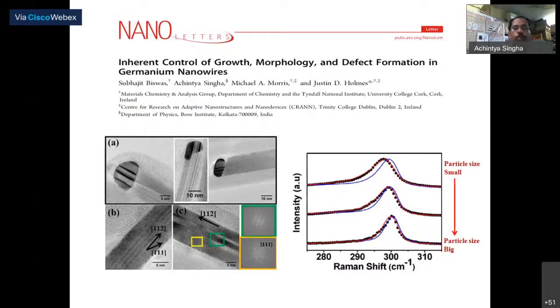Yeah, here is the example of germanium nanowires of different size. You can see the Raman spectrum on the right side of the slide. You can see that the particle size is decreasing. The upper one is the small particle size, and the lower one is the biggest particle size. When the particle size is big, it is more symmetric, and as we decrease the particle size, this asymmetry appears. From this we have estimated the particle size, which is from 5 to 10, and it is also consistent with the TEM analysis of the sample. Okay, go next.